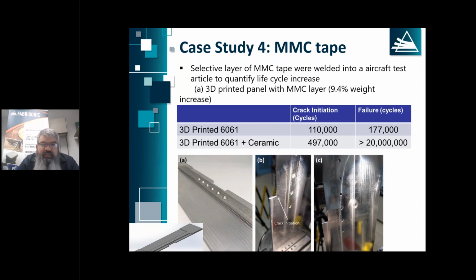The monolithic printed 6061, we started seeing cracks at 100,000 cycles, and we had 2 parts by about 200,000 cycles. But by adding just a little bit of ceramic fiber, the crack initiation pushed out to about 500,000 cycles, and we actually ran out of test money at 20 million cycles. So again, by combining dissimilar materials in a very specific way, you can get huge gains in performance. And we do a lot of work with metal matrix composites, with very elegant designs, by using UAM to combine the dissimilar materials to get a much more effective, more optimized structure.